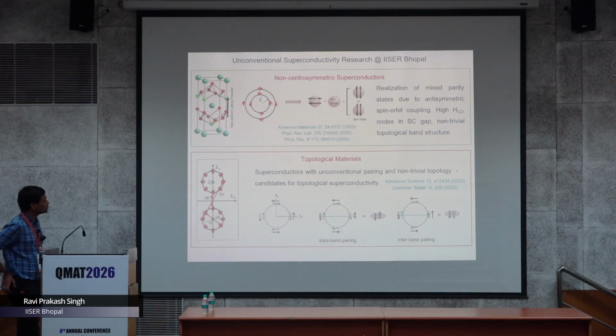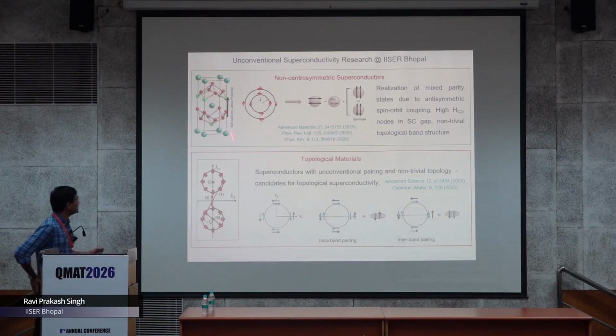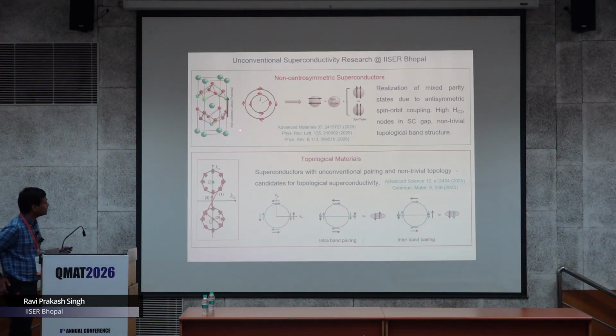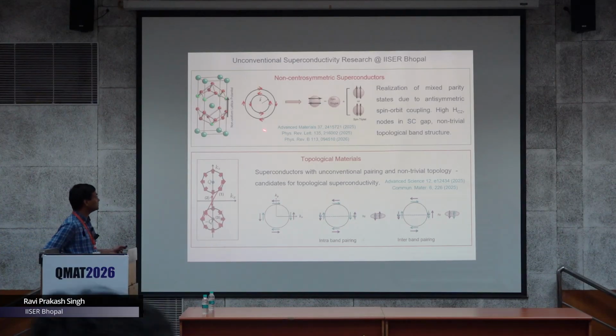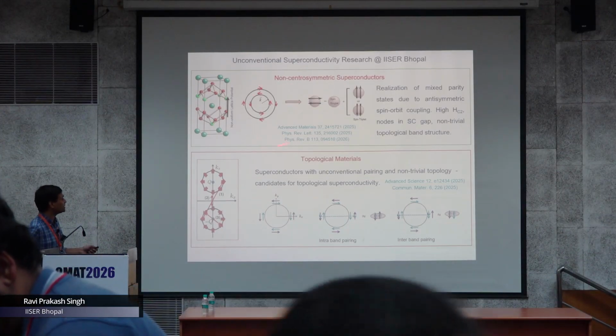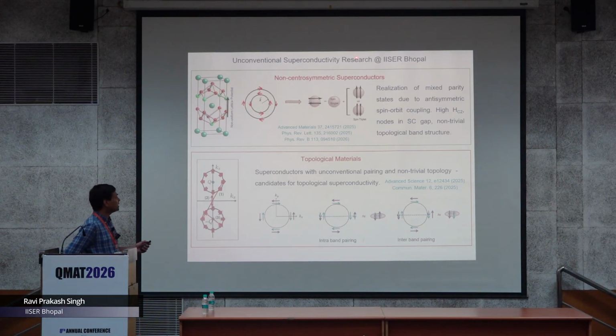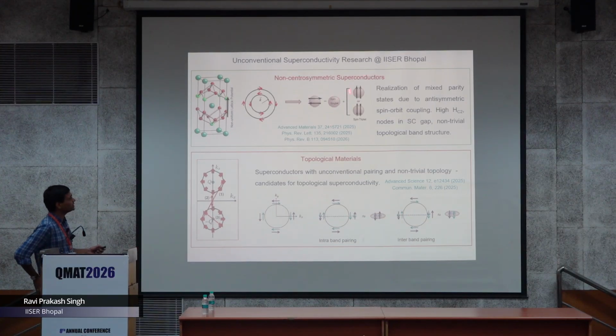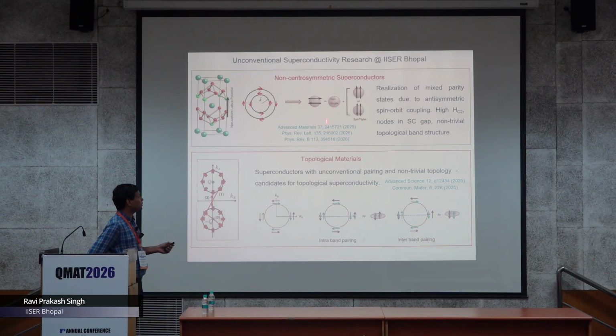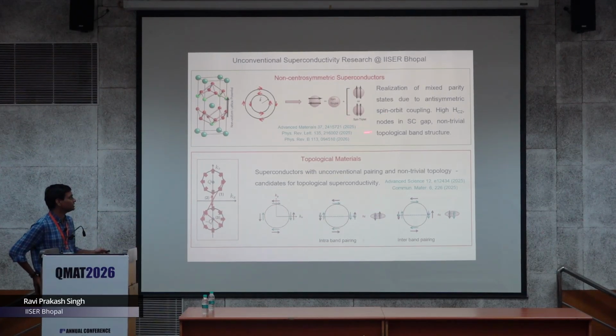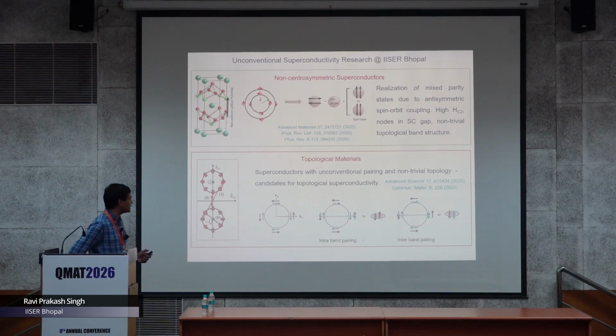The first system we have been working on from the beginning, for the last 10 years, is the non-centrosymmetric superconductor, because you have a non-uniform lattice potential. If the center of inversion is not present, then you can get a non-uniform lattice potential, and parity is not a good quantum number. Then you have the possibility of spin singlet and triplet. Our idea is how we can tune this ratio, and basically you can tune it by tuning the spin orbit coupling.